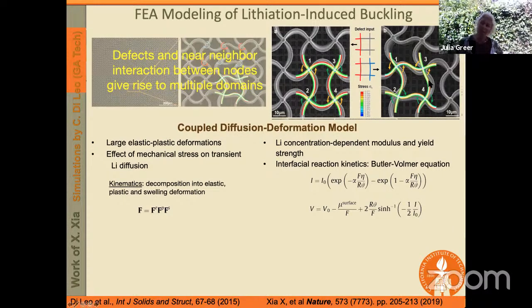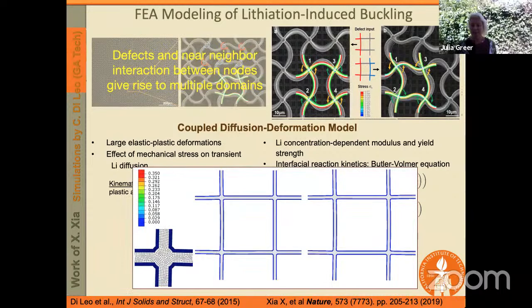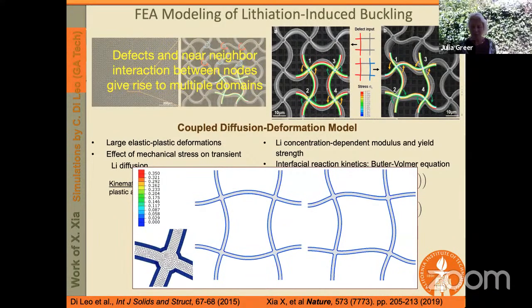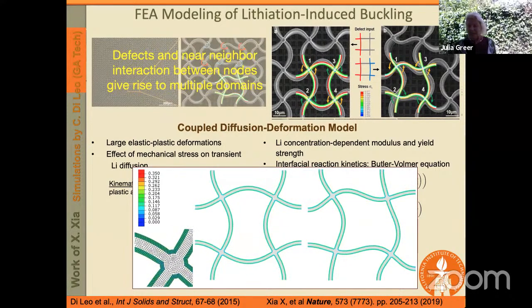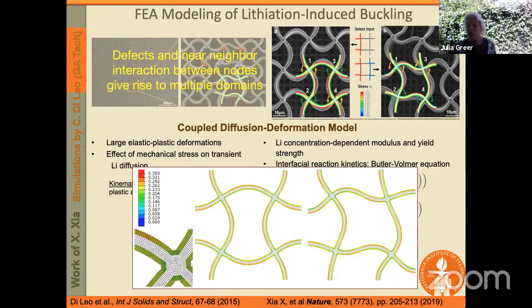And I would like to point out, this is not elastic buckling. This is actually yielding. The material is yielding as the lithiation is occurring, and the lithiation front is progressing through the beams from the outer surface towards the inner part. So we collaborated with a research group at Georgia Tech that created these patterns as a function of lithiation. So you can see the color changing. That's the amount of lithium that's going in. And of course, it's changing the composition of the sample.